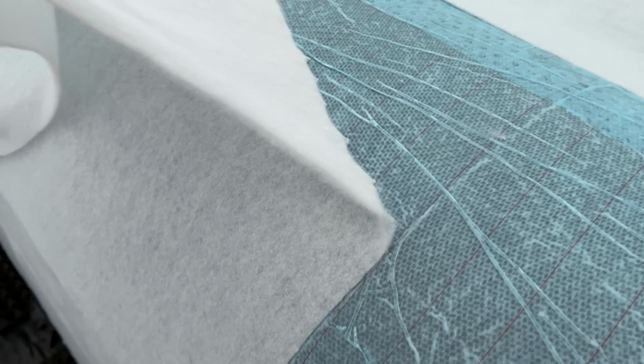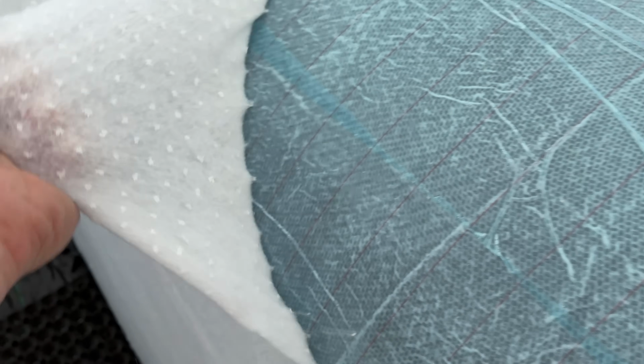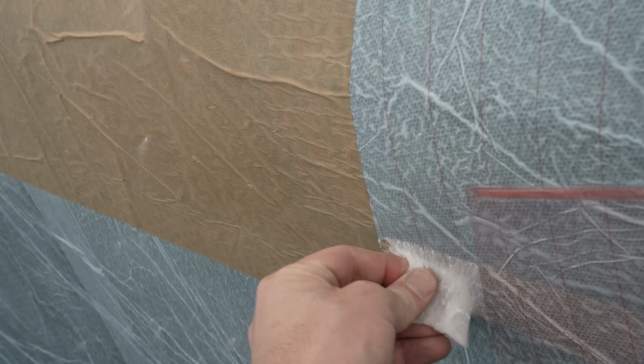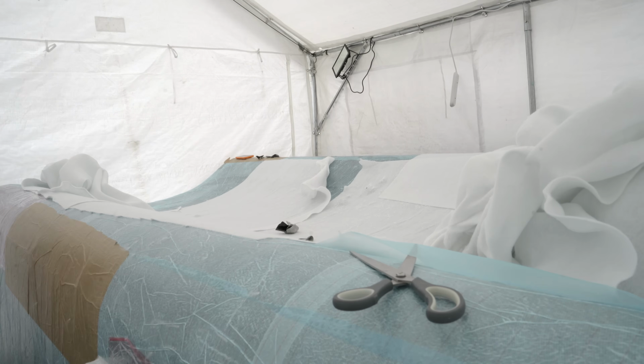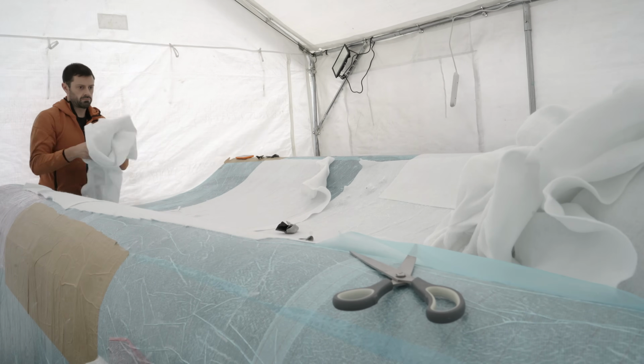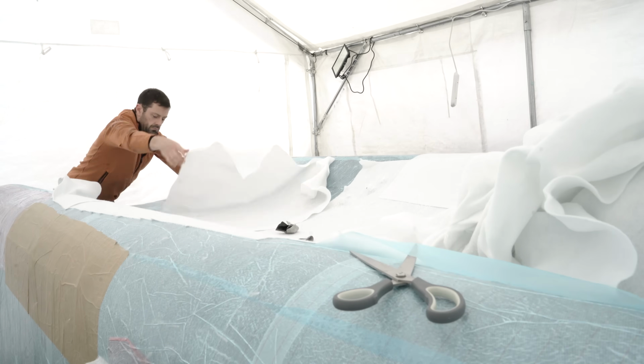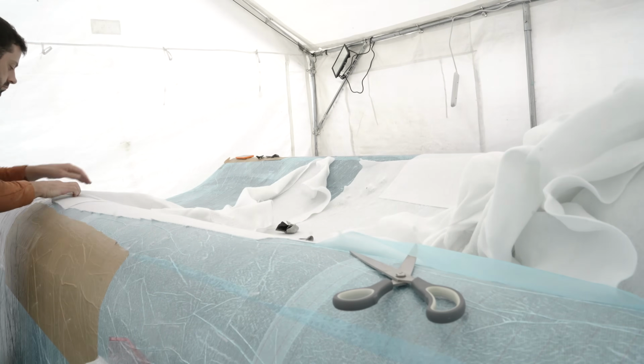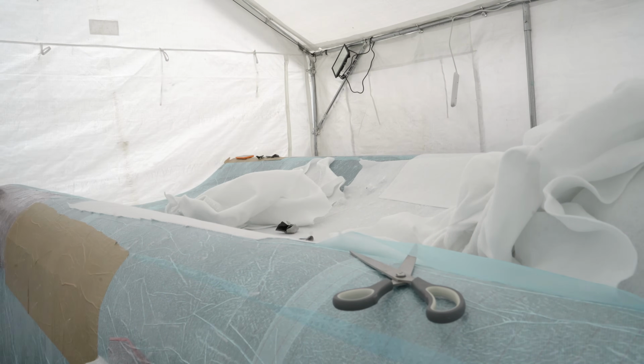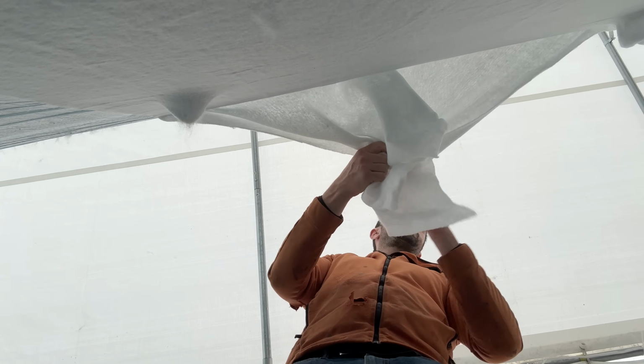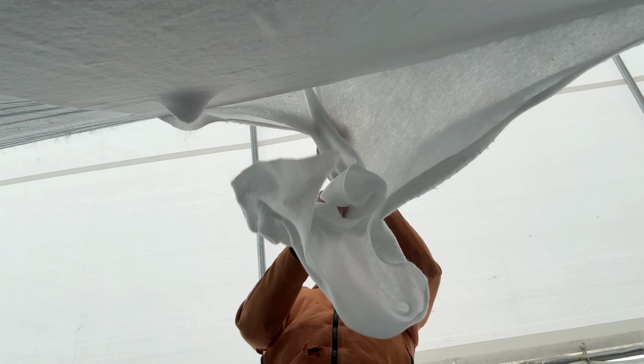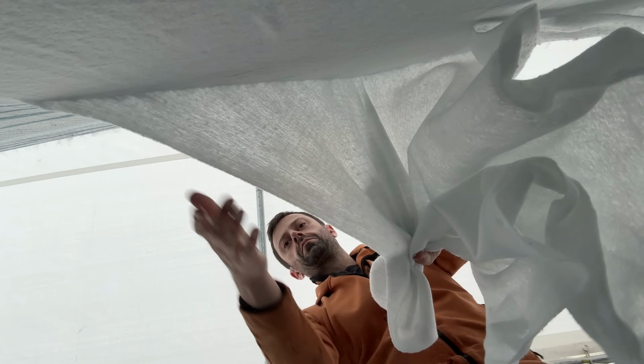Most sections, even the verticals, had a fairly good amount of resin transmission through the film, and only a couple of spots we neglected to add film, which highlights why you do need it. Otherwise, too much resin flows into the absorbent breather. Where holes have been punched every couple of inches and not every few millimetres, there's a chance the part will be a little more resin rich, so heavier without benefit. That's to be avoided at scale. Let's tidy that up, and time for a jaunty camera angle of the same work that I no longer have any deeply cerebral nor reflective voiceover comments to run alongside.